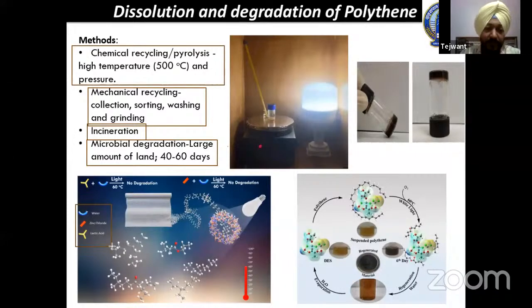So we have utilized the deep eutectic solvent comprising zinc chloride and lactic acid, which absorbs moisture from air. That is why we have also shown the presence of water there. Once you put polythene in this deep eutectic solvent and heat it at 60 degrees Celsius under visible light, as shown in the middle diagram, you can see the polythene gets dissolved. It not only gets dissolved, the polythene gets deteriorated to smaller units and functionalized to become more polar. Polyethylene is very hydrophobic in nature.